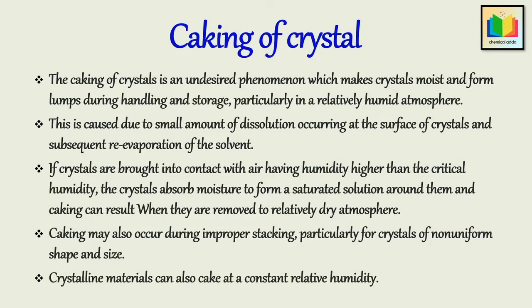When the particle size is non-uniform, a crystalline material will cake more rapidly, because the porosity of a bed of particles of mixed sizes is less and fine particles are more readily soluble. Thus, the tendency of crystalline materials to cake can be reduced by forming crystals of relatively large and uniform sizes, or by adding a water-repellent agent such as stearic acid.